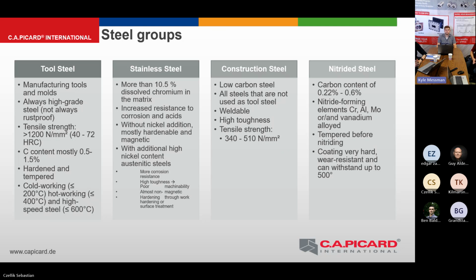And they are divided in 3 groups: cold working, hot working, and high speed steel. That only means at which temperature they could be used. Then we have stainless steels, and please, I know many people think stainless steels are always rust free, but that's not really true. I will show later why they can rust. But what they all have in common is that they have more than 10.5% chromium. And because of that, they build a passive layer on the surface that is protecting the steel against corrosion or acid. And there are 2 different types of stainless steel.